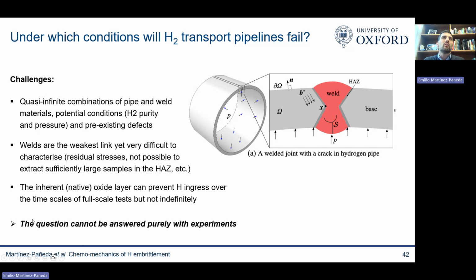The other problem is that what is going to fail first are the welds—they're the weakest link in the pipeline, mostly the heat-affected zone, this area where things become brittle and hard. But the heat-affected zone is very small, so we cannot really extract potential samples to do fracture experiments there. And even when you do full-scale experiments, it's a bit difficult because you have a native oxide layer that might prevent hydrogen uptake over the duration of your full-scale experiment, but not over the duration of the decades that we want to transport hydrogen in pipes.